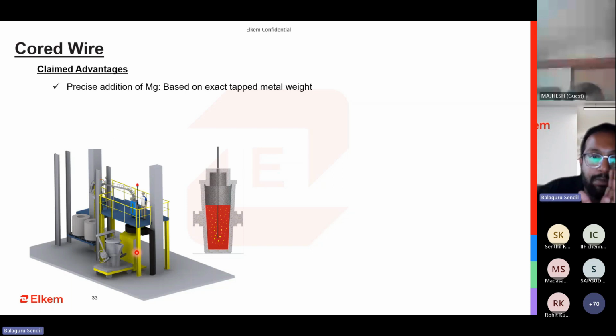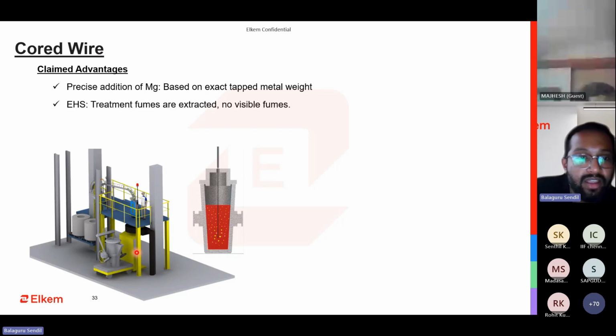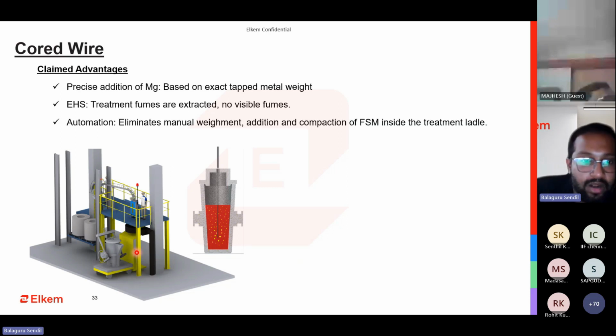Most of the foundries, they tap for melt 500 kgs and then melt 1000 kgs and then tap 500, hold the remaining 500 and then tap again. So they don't know exactly how much is being tapped. There's always a plus or minus 50 to 60 kg and the addition percentage, they have to compensate for that. But in cored wire, they claim it is a very precise addition of magnesium and it is environment friendly. There is no visible fumes and it is fully automated, no manual weighment, addition and compaction of FSM inside the treatment ladle pocket. These are some of the advantages that are claimed.